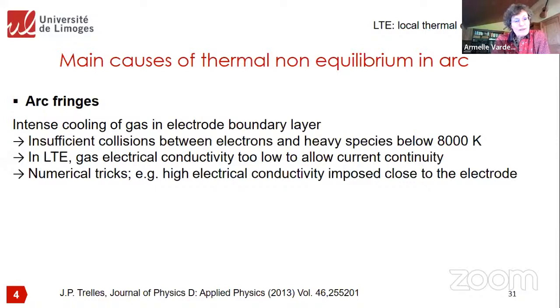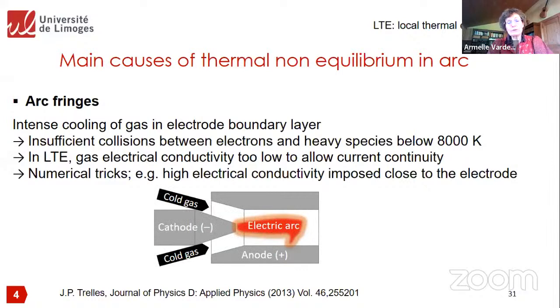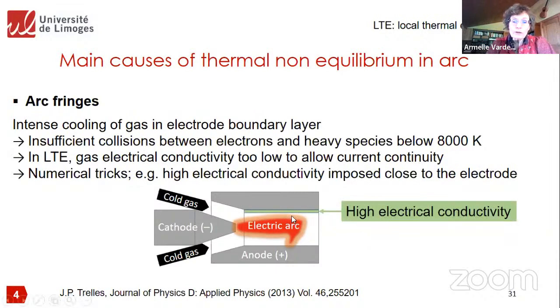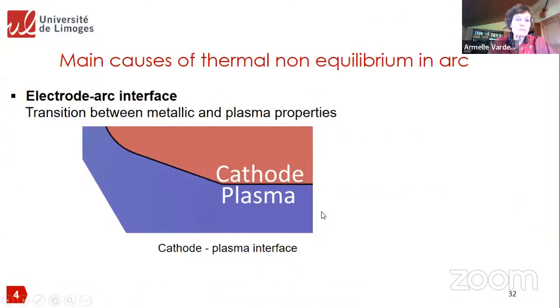In that case, the electric conductivity of the gas will be too low to allow the current continuity. So if you use an LTE model, you have no choice. You need some numerical tricks to have the continuity of the current between the arc column and the anode. Generally, the most used is to impose some high electrical conductivity close to the anode wall to allow the arc to go through this cold boundary layer.